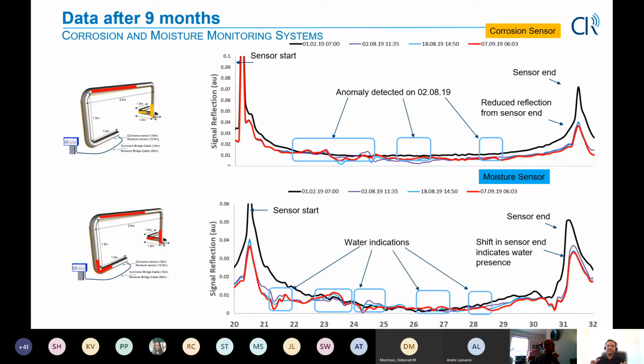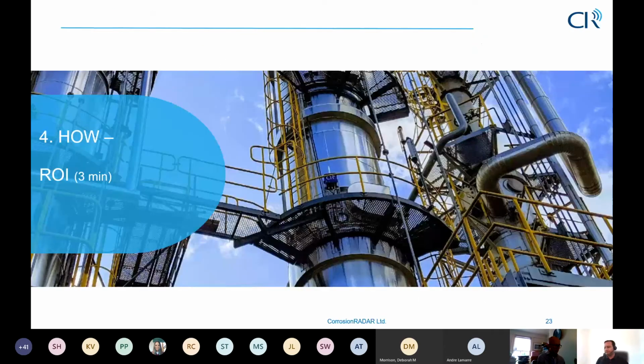Now, there are multiple angles here. One is this shows the end user that rather than periodic inspection, they're already seeing corrosion, say water coming in, so they should be inspecting those particular locations at the next cycle. Of course, with corrosion rate, they can get that risk as well. The second is, if this had not shown any water, we would not have recommended any inspection at all, so they would have saved the cost of unnecessary inspection. So both ways. But in this case, since a highly localized region is identified, they will probably do a very precise inspection, say either visual inspection or using pulsed eddy current or X-ray at those locations. That's the power here: this is a pre-screening, risk-based identification tool, and then a validation is required.